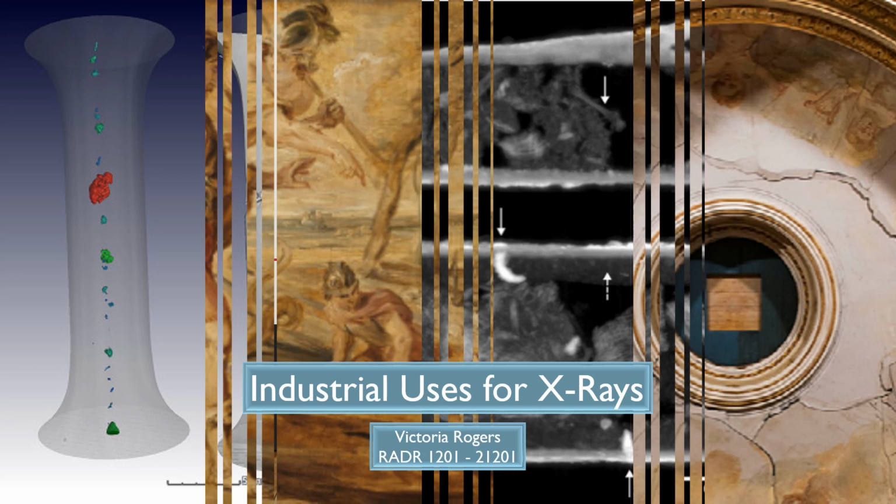Tomography dissects a solid structure into different planes, similar to how an MRI creates a complete picture from multiple images. The 3D image reveals porous layers hidden in a column, with most defects being small and inconsequential to stability. However, a larger red imperfection in this area may cause a fault and potential failure. Armed with this knowledge, the building team can reevaluate their process and construct a stronger support.